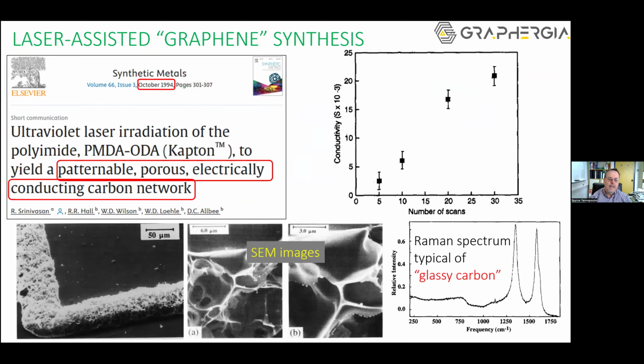This slide is just to provide you a visual reminder of the early works of this field. You can see here that already in 1994, 20 years before the term LIG was coined, researchers were able to use UV lasers to irradiate Kapton and provide what we know today as three-dimensional porous graphene-like structures. This is important because it shows that laser-driven conversion into conductive carbon networks has some deep roots. It did not suddenly appear as a completely new concept in recent years.